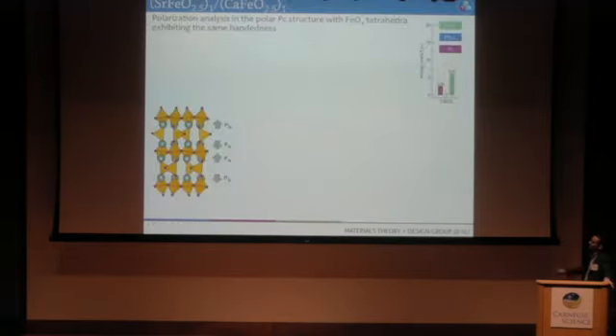And so what I want to do is look in a little more detail at this 1-1 period superlattice. It's a little simpler to assess, at least in a presentation. And these are the energetics from the previous slide. In the unordered, the non-chemically ordered structure, we have, again, I remind you, two types of A distances. We have short ones and long ones. And these give rise to compensating layer dipoles.